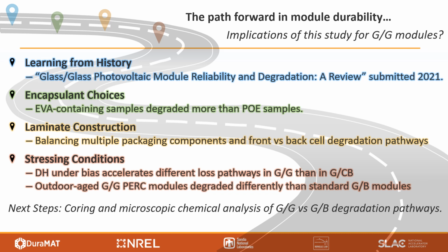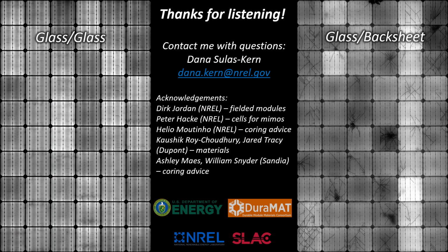We also showed different degradation pathways depending on the laminate construction, particularly how backside loss pathways change when you have a rear side glass sheet rather than a clear back sheet. And finally, it's obviously important to note that the module construction will have to be optimized depending on what stress conditions the module is expected to experience. In our studies, we highlighted the different impacts of PID, moisture ingress, and mechanical strength that vary between glass-glass and glass backsheet modules.